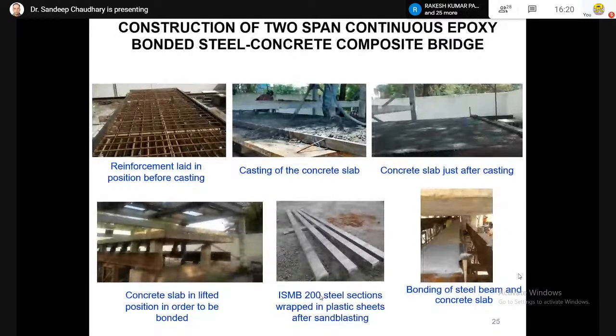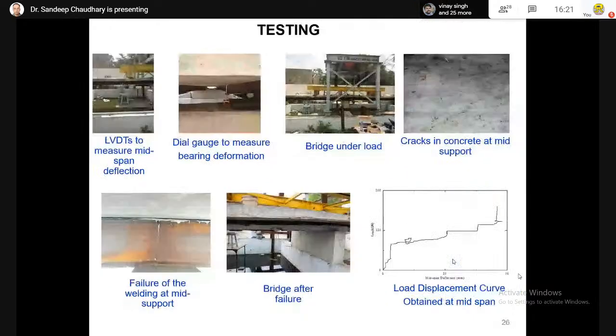And here we are seeing the reinforcement laid in position before casting of the concrete slab, and the concrete slab after casting. And you are seeing the concrete slab in a lifted position so that it can be bonded. There were ISMB 200 steel sections. They were wrapped, of course, in plastic sheets after sandblasting. Sandblasting was done on these steel sections to ensure a proper bond between the concrete slab and steel girder. If sandblasting had not been done, maybe the epoxy would not have had proper bonding between the concrete slab and the steel section. And in the last figure, you are seeing the bonding of the steel beam and concrete slab going on. Here the concrete slab is now being lowered, and epoxy has already been placed on the steel section. And once the concrete touches that, there will be a perfect bond between steel girder and concrete slab.